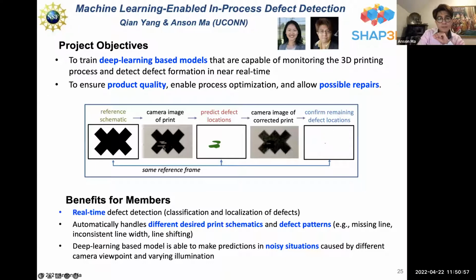You can see, for example, I have some defects here, right? There are some lines that are defective because I have missing black lines. This is what I want to print. This is what I have now. What the machine learning code allowed us to do is identify where the defects are. Of course, we can improve the accuracy a little bit more. But once you know where you have the missing dots, you can come back and repair it, and then you check again and say, okay, now it looks pretty good. Again, there's some work to be done in improving the accuracy of the defect detection part.